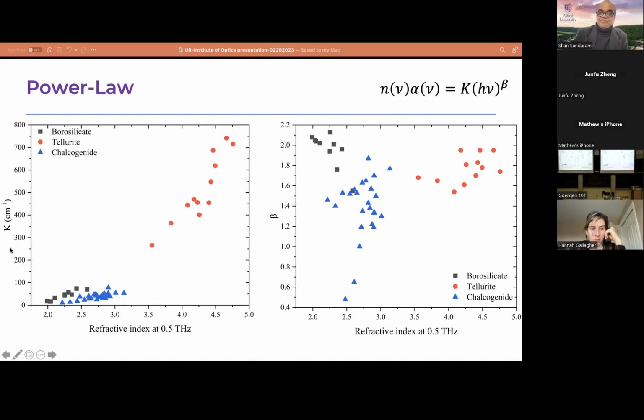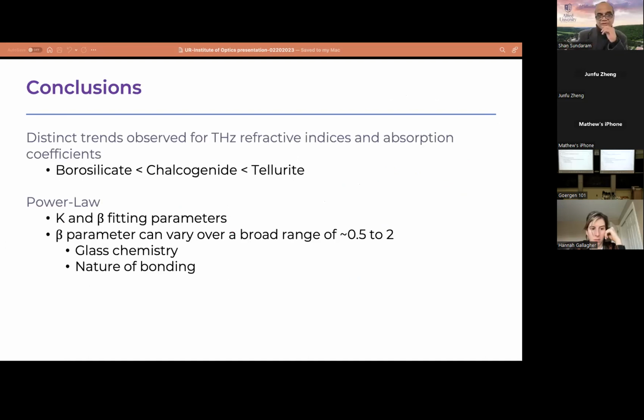Okay, so in the K factor, we find again a clear clumping of borates and chalcogenides and the tellurite family separately here. So you can see once again, I can use these fundamental parameters to recognize the group of glasses. I will be able to pick and choose and predict or even design to get the property I want. So concluding that part of it, the fitting parameters were calculated, but our data at least shows one big trend: the borosilicates definitely are, there's a decreasing trend between borosilicate, chalcogenides, and tellurite, if you're looking at refractive indices and absorption coefficient values. And the fitting parameters fit well, but the beta parameter is a very strong function of glass chemistry and glass structural units, anywhere from 0.5 to 2. It's not just around 2, as predicted by the power law, the original power law reported in the literature.